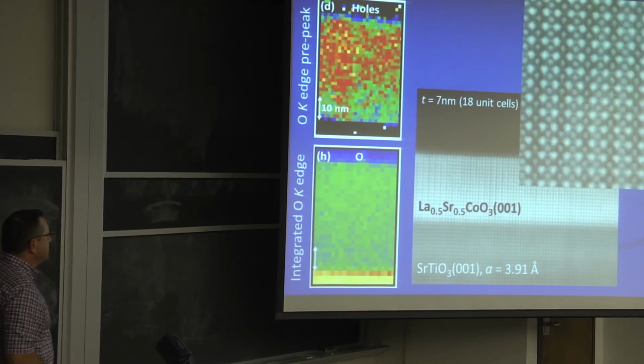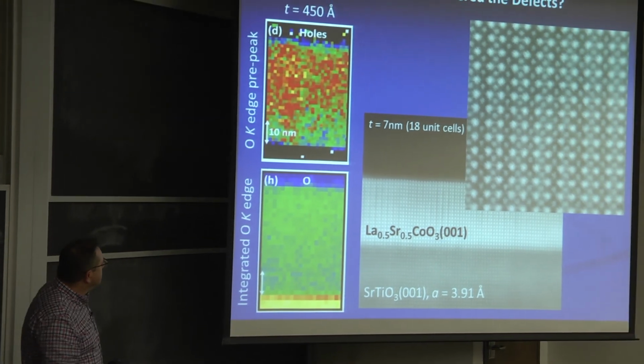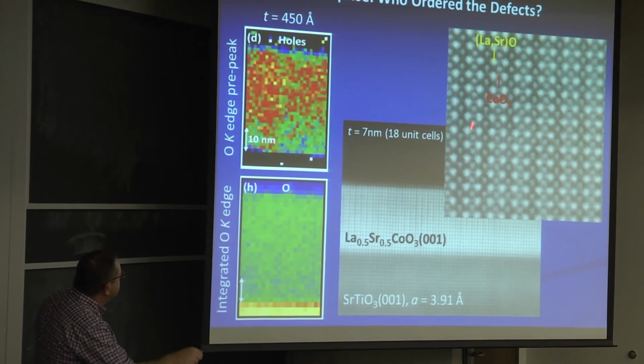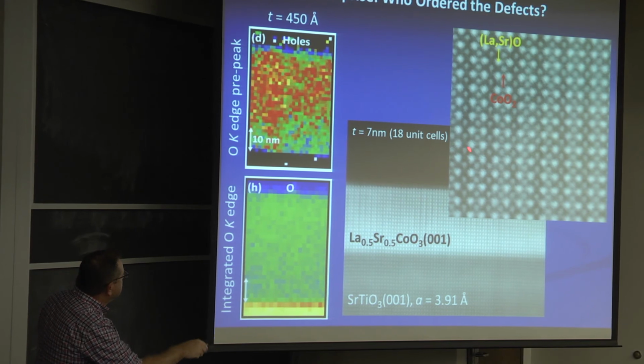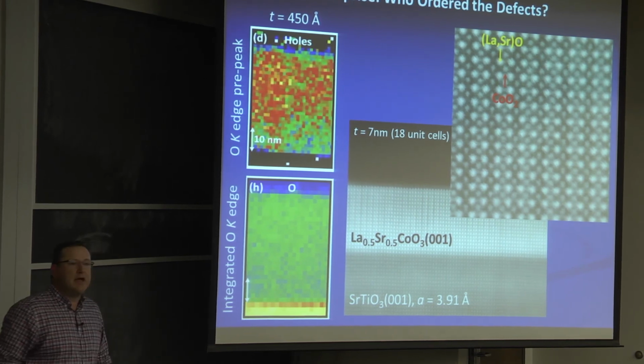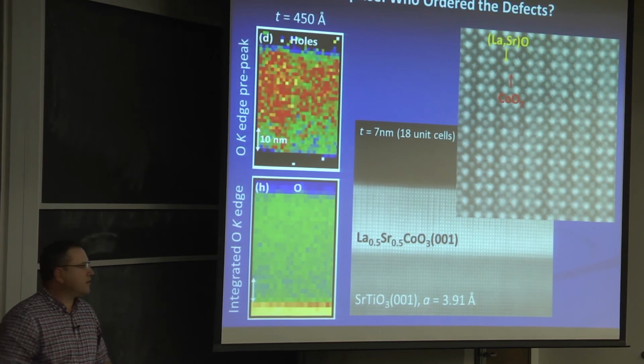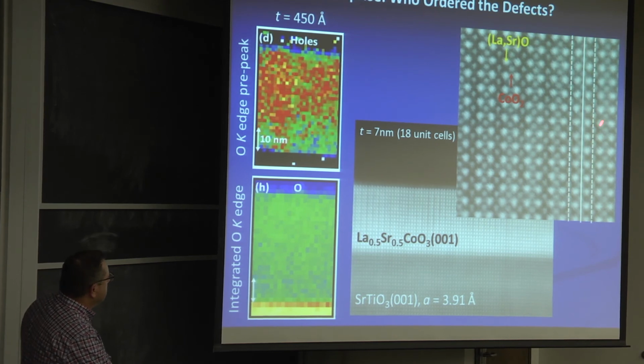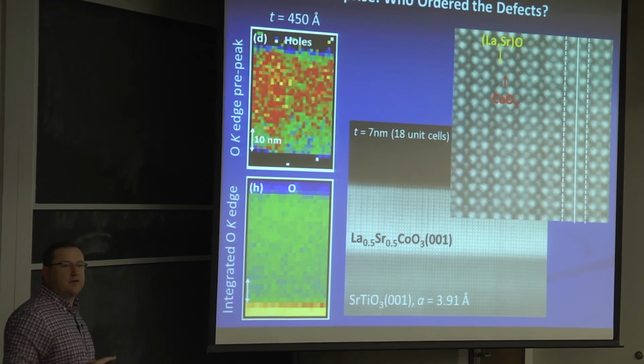So we amplify this image. This is really sort of amazing. You can go in, pick out the atomic columns. This is the cobalt oxygen column. This is the lanthanum strontium oxygen column. And you realize this is all about the cobalt oxygen column. The cobalt oxygen column basically goes dark, bright, dark, bright, dark, bright, dark, bright in exact alternation.